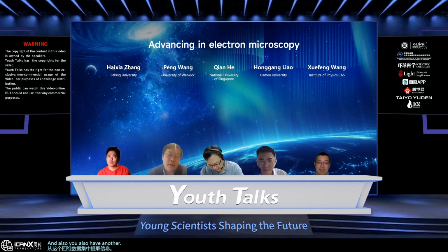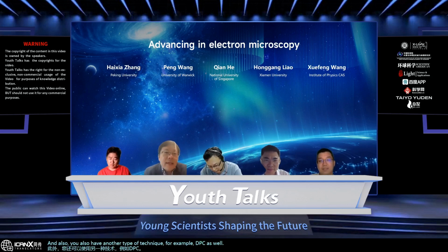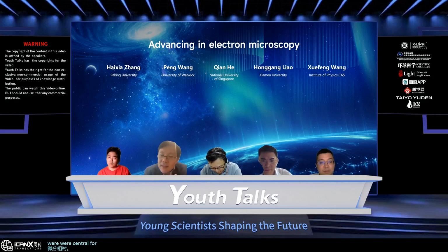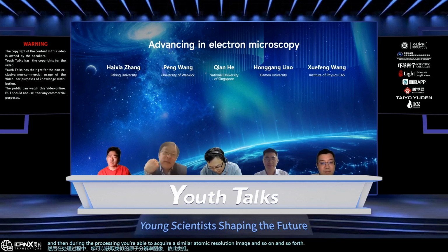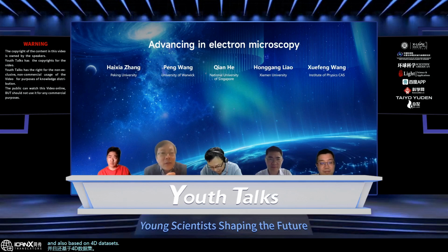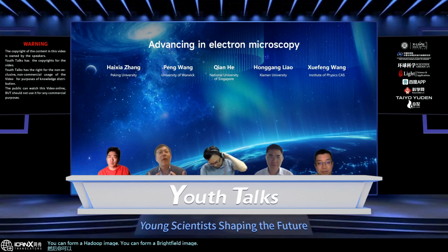And you also have another type of technique, for example DPC as well, right? Differential phase contrast or center of mass method, which is also based on 4D STEM datasets. During the processing, you're able to acquire a similar atomic resolution image and so on. Also, based on the 4D dataset, you can do virtual imaging. You can integrate part of the area of the diffraction pattern and form a dark field image, or you can form a bright field image, and that's what we call virtual imaging based on a 4D STEM dataset.